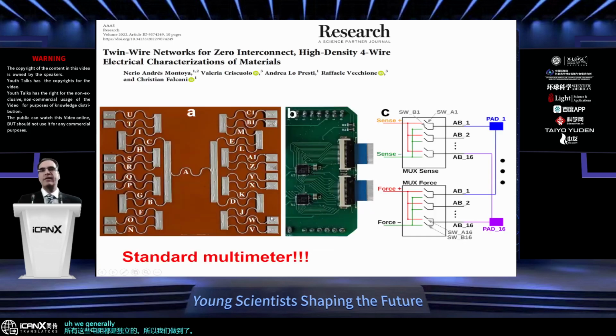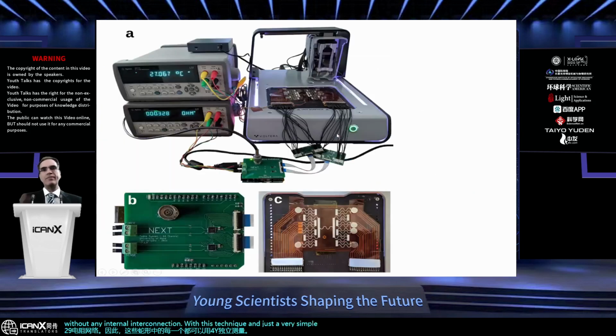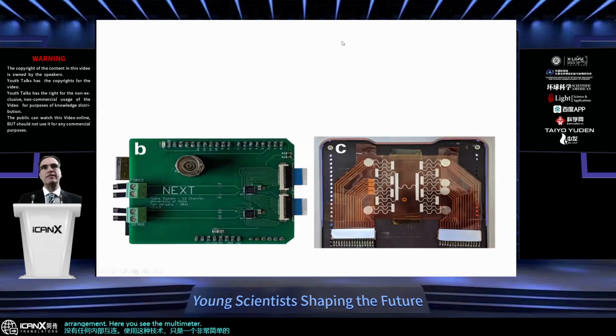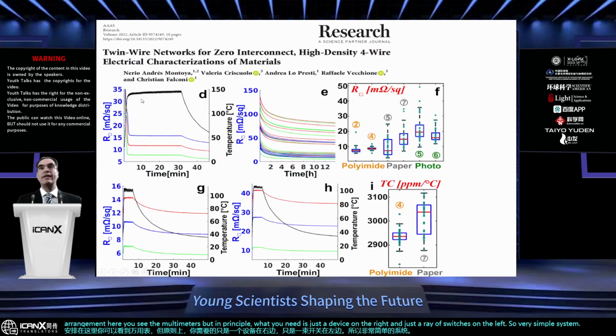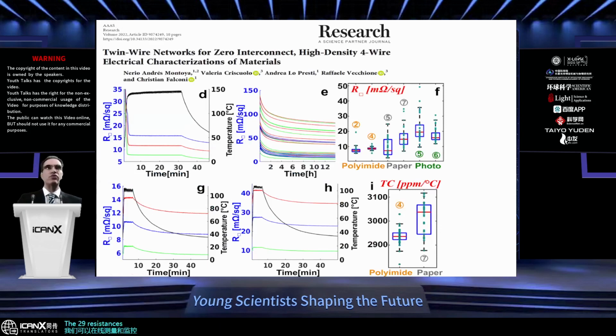We generalized the process for fabricating such networks. And here you see a twin-wire 29-resistor network. Every single one of these serpentines can be independently measured with 4-wire without any internal interconnection. With this technique and a very simple arrangement, here you see the multimeters, but in principle what you need is just a device on the right and an array of switches on the left. So it's a very simple system, and we could monitor online the 29 resistances, for instance, during sintering.